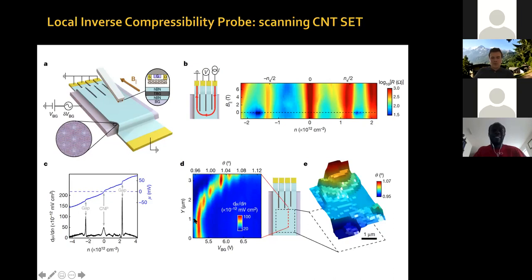Now, you can, for example, look at this peak in the inverse compressibility as a function of position. So you can take a scan, where Y means Y micrometers across a sample, and as a function of density you look at the scan and you track this peak. You can see that for the first micron, the sample has a peak at a given density, at a given gate voltage, which corresponds to a given twist angle. And then this thing shifts sideways, which means the twist angle is changing rapidly in this region.